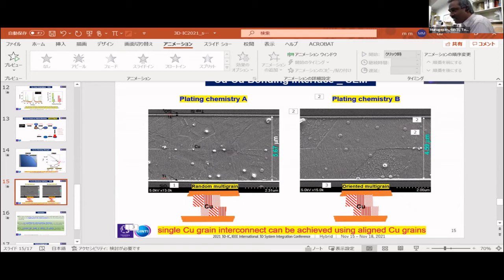Oriented, obviously, because it's not at all aligned before bonding itself. So there is hardly any bonding, I mean, copper diffusion or single grain growth between the top and bottom die. On the other hand, if you look at the right side, this is our new plating chemistry. As you can see, as I showed with our copper grains from the XRD structure, it is either 100 or 110 oriented. So obviously you see a very nice single copper grain connecting your bottom die and top die. So that's our aim.